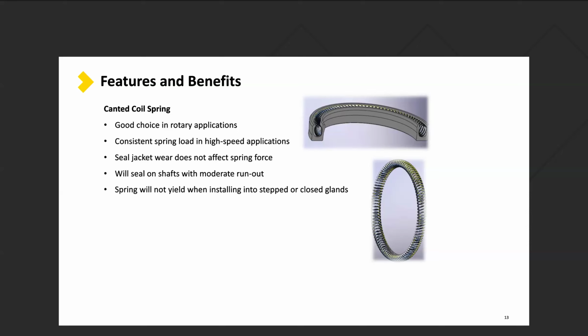A couple of other benefits of that spring: we talk about run out, eccentricity or misalignment. Now, no spring energized seal is good under those conditions, not because the spring can't react, but because the jacket materials that are used are very slow to react. An elastomer springs back very quickly, so you can handle some of these run out conditions. A spring energized seal made of PTFE reacts very slowly. So if there is a spring that's better in a run out condition, it would be the canted coil, although I would not say that if you have a known run out condition that a canted coil spring energized seal is going to solve that. There may be some other things that need to be done.